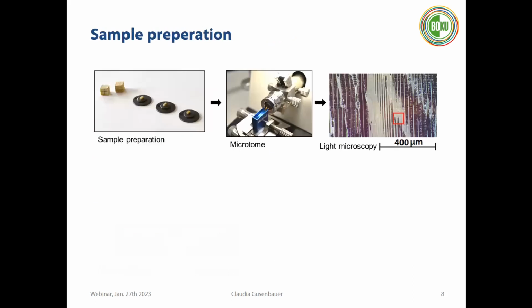And to prepare such samples, we need to microtome them. So in the first step, we take some small wood pieces out of our material, we glue them onto these metal discs, and then we can cut them with diamond knives. So we have very sharp knives, which deliver the needed flat surface for our AFM measurements.